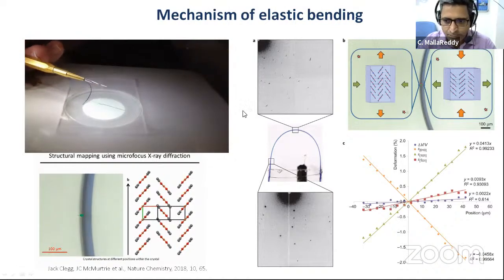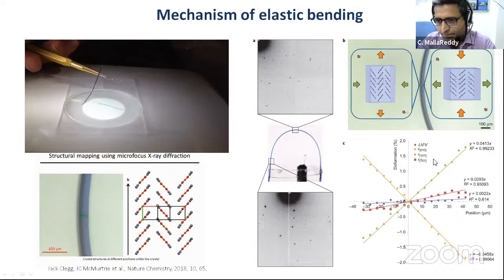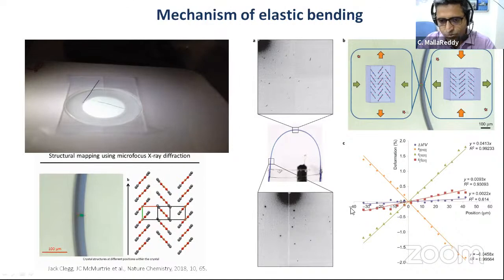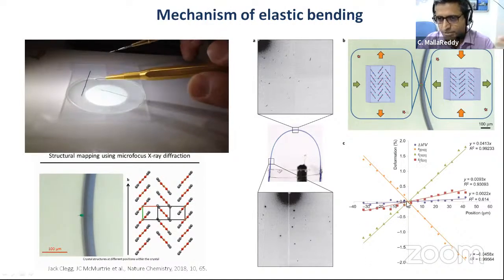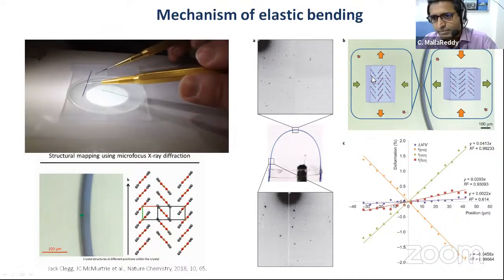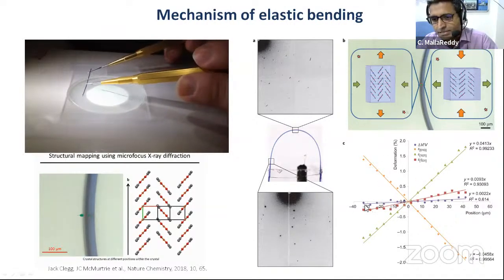So this was done by the Australian group, and then they have again compared the changes in the unit cell and plotted all these, and showed that the different axes, the unit cell parameters, change, but the volume more or less remains.